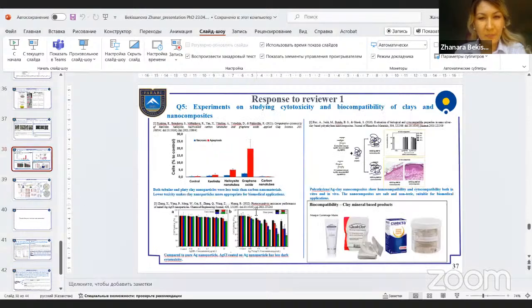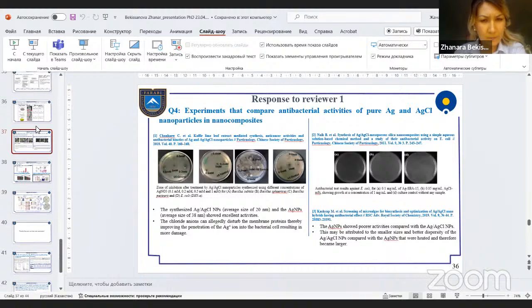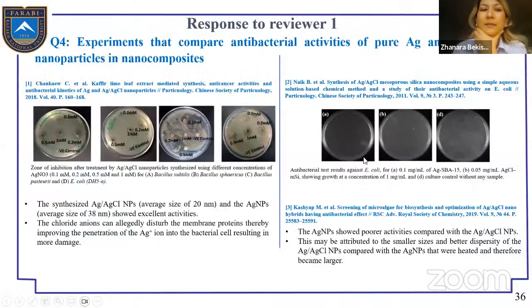Thanks for the question. About separating the silver chloride and metallic silver nanoparticles: the hybrid particles of silver chloride and metallic silver which we obtained, the results show that the hybrid particles have more cytotoxicity than metallic silver or the silver chloride nanoparticles. The hybrid particles show a synergistic effect. It is a new trend of study, rather than only pure silver and pure silver chloride.